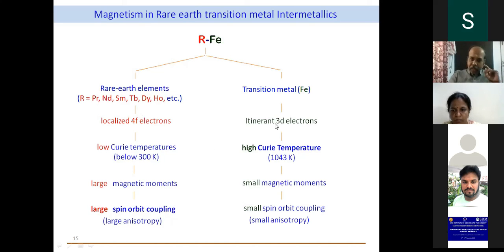In the case of a transition metal, it has itinerant 3d electrons, the Curie temperatures are high, the magnetic moments are low, and the spin orbit coupling is relatively low. So now when we combine these two kinds of materials, a rare earth which has high anisotropy and low ordering temperature, with a transition metal which has high ordering temperature and low anisotropy, we get magnetostrictive materials with moderate magnetostriction which work at room temperature. That's how the alloy design of these materials has been predicted, modeled, and finally fabricated.